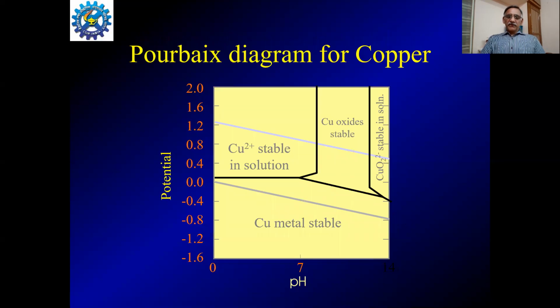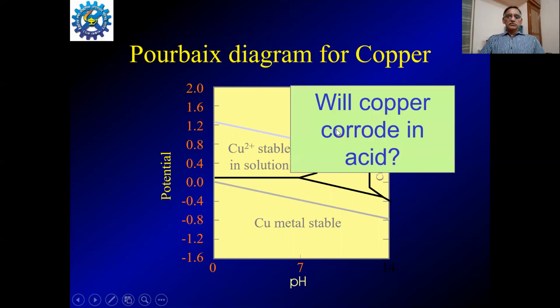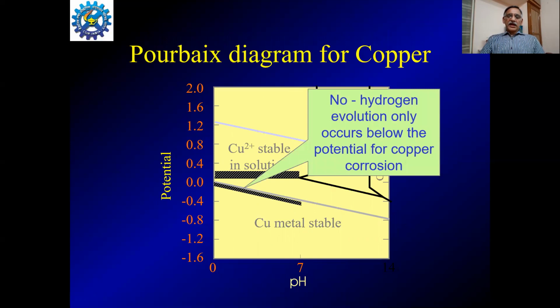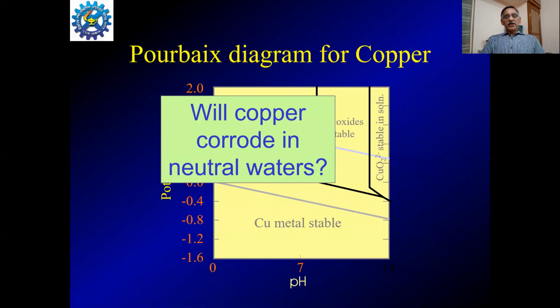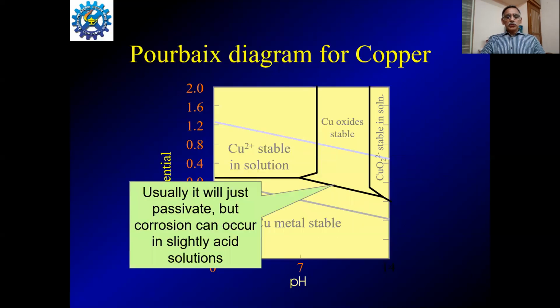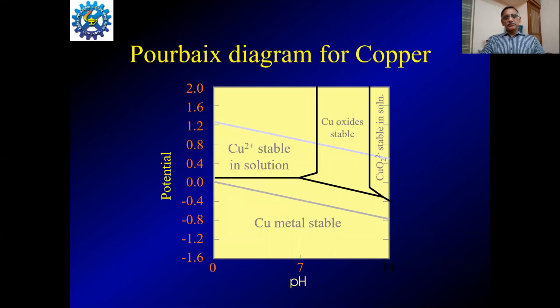Similarly, for copper, we have the copper potential-pH diagram: copper metal stable, copper 2+ stable, copper oxides. Again, here you can see this is the immune domain, this is corrosion, this is also corrosion, and this is the passive domain. Will copper corrode in acid? No, because the hydrogen line is well within the immune domain. So hydrogen evolution only occurs below the potential of copper corrosion, and hence copper will not corrode in acid pHs. Will it corrode in neutral? Usually it will just passivate, but corrosion can occur in slightly acidic solutions.